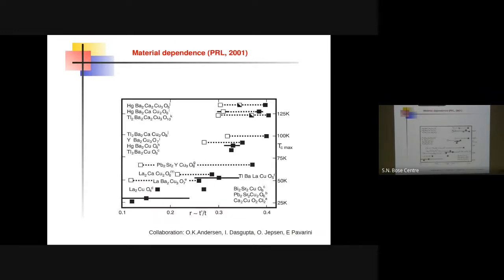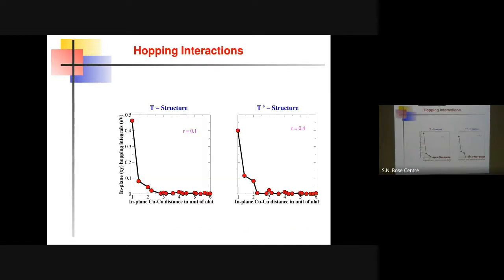And we actually calculated it for nearly all known hole doped cuprates, and through such Wannier function construction, we extracted this range parameter, and we found that the range parameter actually correlates with the Tc at optimal doping. Higher is this range, better it is for achieving higher and higher Tc. Now back to this T and T prime structure. We find if we calculate the r parameter for the T structure, as you have already seen from the Wannier function plot, this is only 0.1, but for the T prime, it's 4 times larger, that's 0.4.